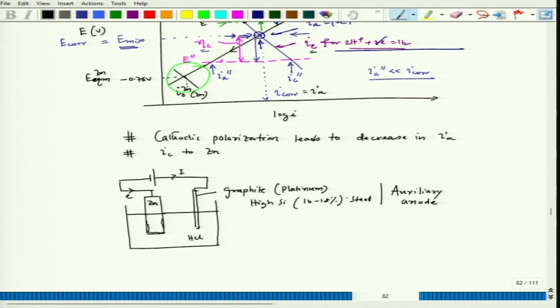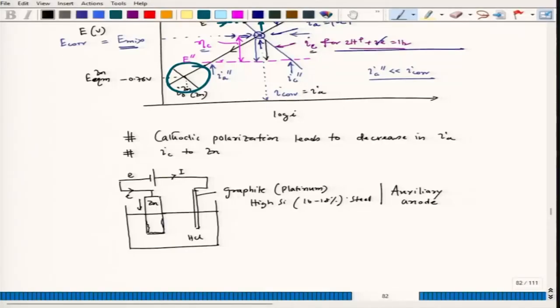Okay. So, now current flows this way, electron flows this way, electron comes over here, and then it actually facilitates cathodic reaction. So, there will be a vigorous hydrogen evolution on the zinc surface compared to the no current situation. But on the way, zinc will be protected, because by that way, if we send current, then the potential is dropped here, and then correspondingly IA has reduced from this to this. So, that way I can prevent the corrosion rate, prevent dissolution of zinc or excessive dissolution of zinc. This is one way of protecting it, or one way of taking the potential of zinc down. And having this polarization happening, which is cathodic polarization, we can have protection.